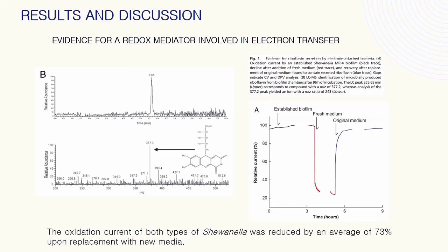Results and discussion: evidence for a redox mediator involved in electron transfer. In figure 1, the oxidation current of both types of Shewanella was reduced by an average of 73%, ±4.5%, n equal to 6, upon replacement with new media. The current was immediately restored to 94% of its initial level, ±6.1%, n equal to 6, after the medium was removed, centrifuged to remove planktonic cells, and then returned to the chamber containing the biofilm with electrodes attached.